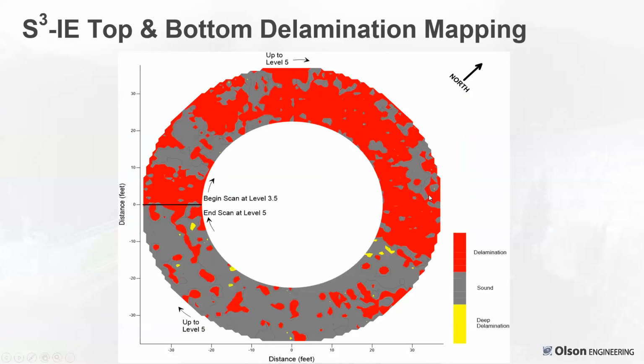So we took all of the results and we mapped them out. This is a single 360 degree rotation of the helical ramp, starting at level 3.5, ending at what's called level 5, mapped out results. And you can see the red areas have surface delaminations. So quite extensive surface delaminations on the northwest side. Down here, these gray areas are sound. There's no damage. There's a small amount of surface delamination.